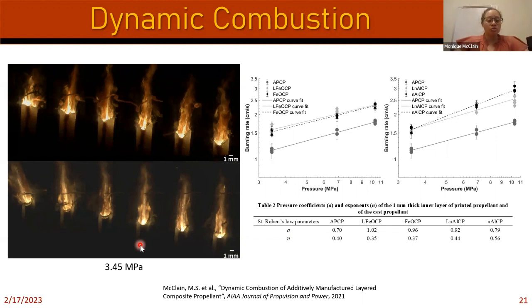Well, when it comes to aluminized propellants, a portion of the burning rate, I think something like 10 to 15%, is attributed to radiation feedback to the surface. So essentially, it will burn about 10 to 15% faster because of that effect. Here, since we only have nano aluminum in about 1/3 of the surface, it's not getting as much radiative heat feedback as it would if the whole surface was full of nano aluminum propellant. So we do see some slight effect here, but in general, adding a small portion of either some catalyst or some nano aluminum to a traditional ammonium perchlorate propellant will improve the burning rate overall of the structure and will increase the burning surface area.